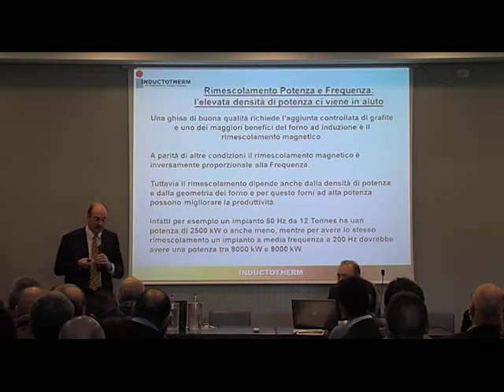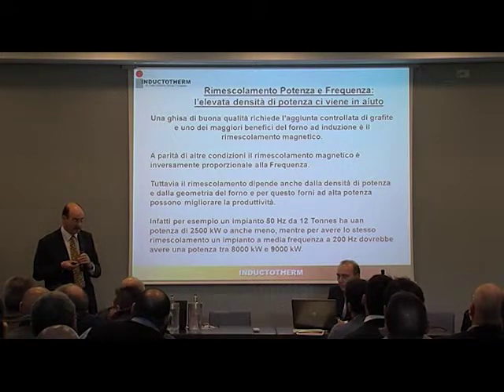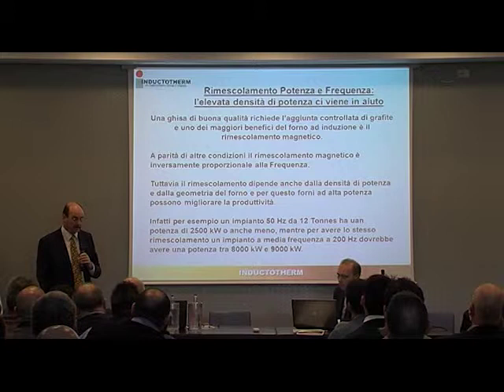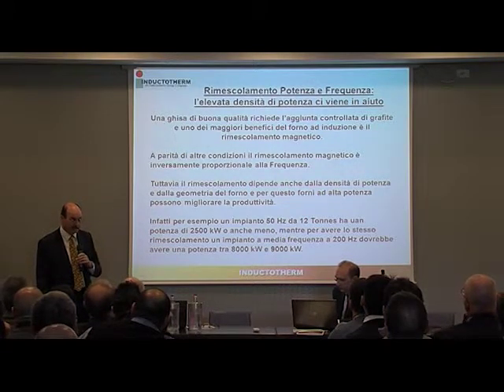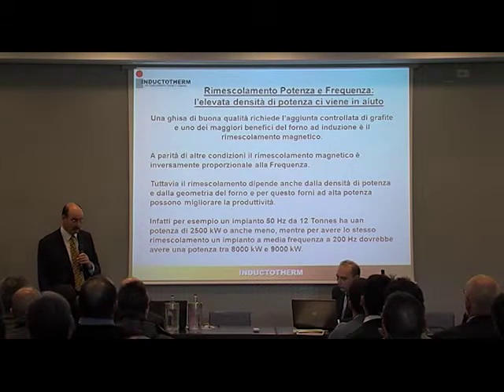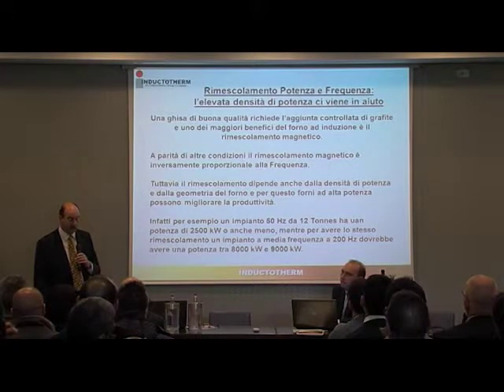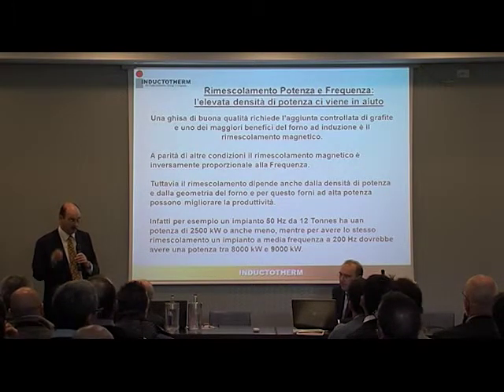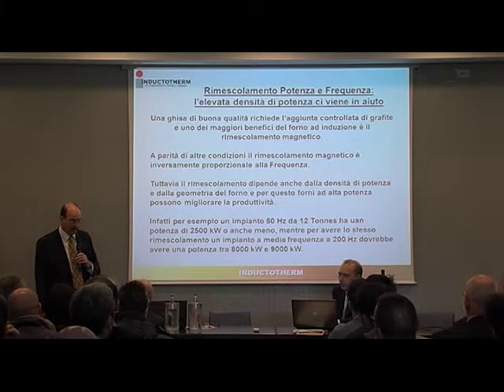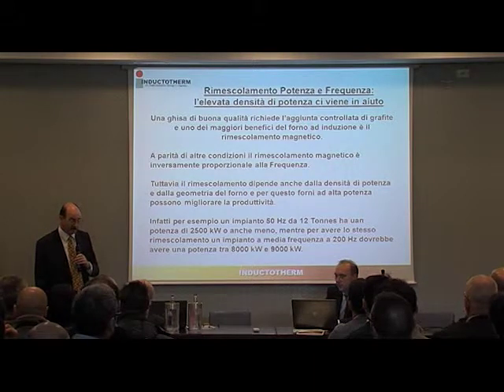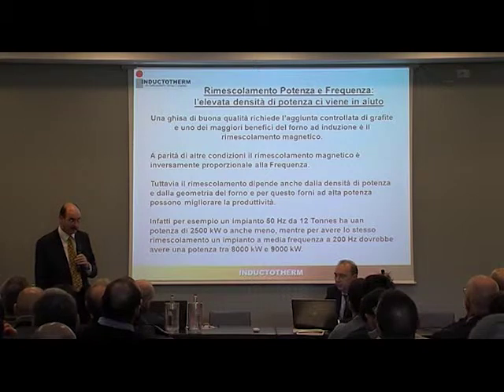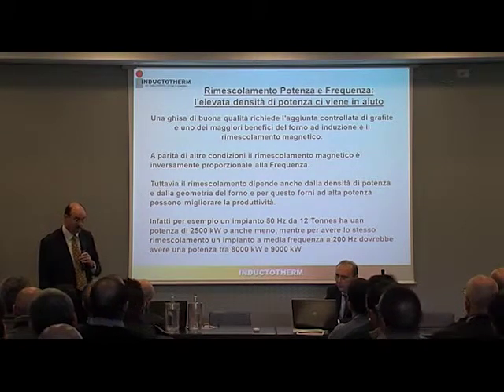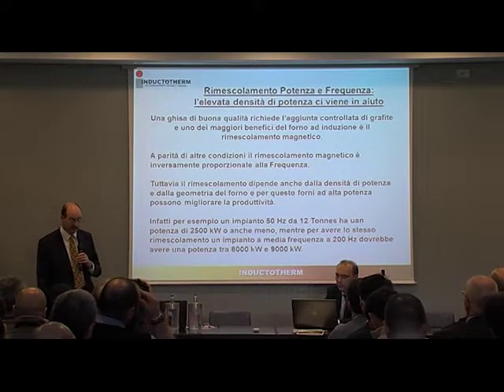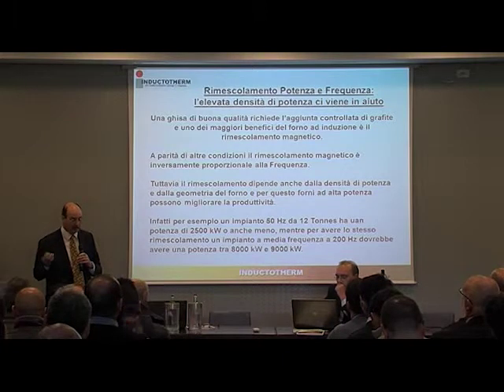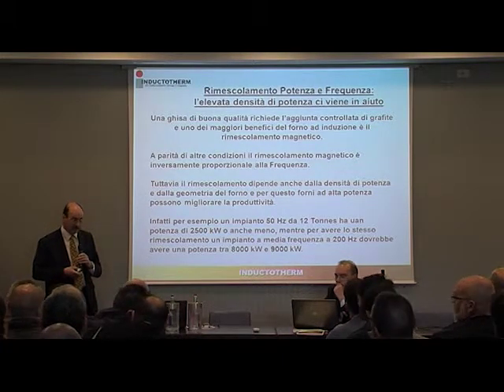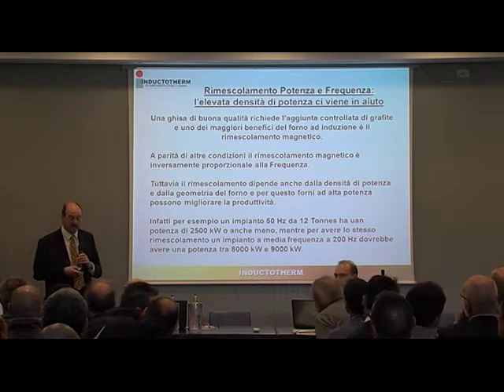Another benefit of high power density is stirring versus the frequency. Good iron quality requires controlled carbon addition, and one of the main benefits of induction furnace is the magnetic stirring that is being created. All other things being equal, the stirring magnitude is inversely proportional to the frequency. So the lower the frequency, the more the stirring. However, stirring is also affected by power density and the furnace geometry, and in this way, high power furnaces can increase productivity. By way of example, the old style 50 Hz furnace with 12 tons would typically have had up to 2.5 megawatts of power on it, while similar stirring from a medium frequency furnace would be between 8 and 9,000 kilowatts.